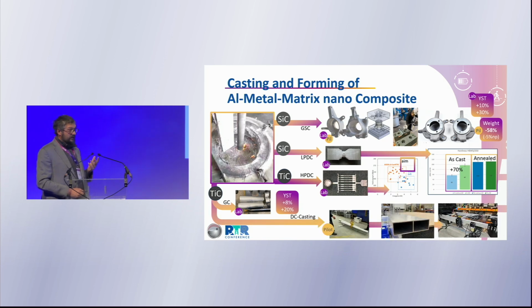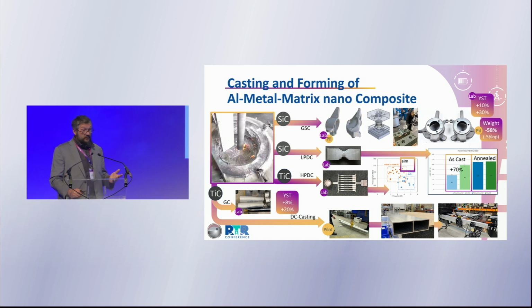This was a problem related to the actual manufacturing process. So instead of having the correct number of nanoparticles in the alloy, which is, by the way, around 1%, we ended up with a bit lower amount. So the final properties of the material were not the same as the lab scale one, but we managed to get an entire rear frame produced with this technique and install it in the vehicle and test it on the field.